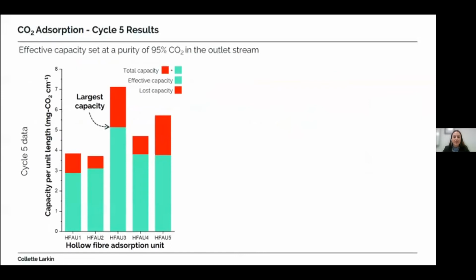So when analysing the performance of the adsorption units, it is important to define a criteria to compare the results against. In the case of CO2 capture systems, the capacity of the unit is important as this represents how much CO2 can be captured by the system. On the graph that I'm showing, you can see in red the total capacity per unit length for the 5 hollow fibre adsorption systems.